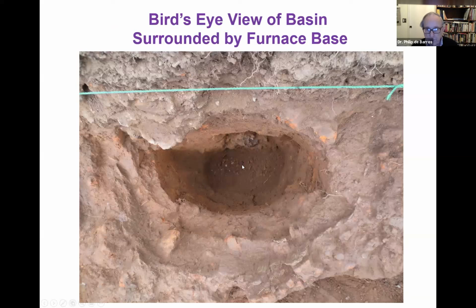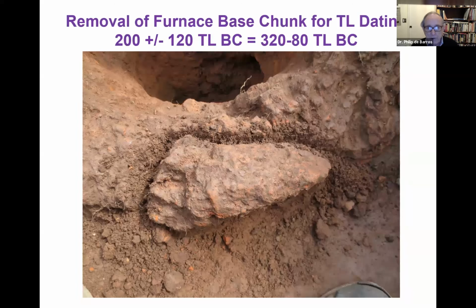So here I've dug into the furnace pit to get slag for analysis, which was published this past year. And here is a piece of the furnace base that was fired really, really hard. It was very difficult to cut it in half for TL dating. And I finally got a date later of 200 BC plus or minus 120, or from 320 to 80 BC, which fits perfectly into the dates based on charcoal and the ceramics that are at the site. You couldn't ask for a better correspondence with thermoluminescence dating, which can date fired clay objects.